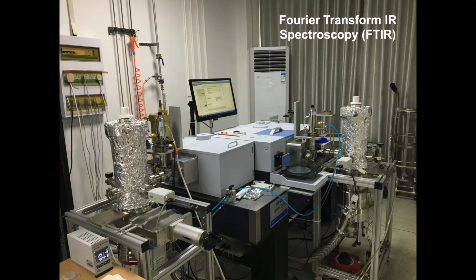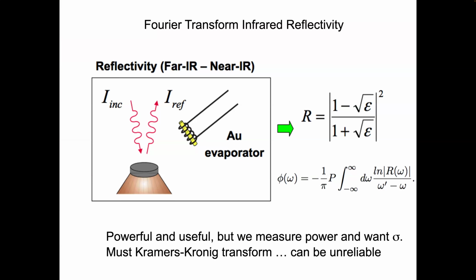And here's an example of an experiment that was done, not by me, but in Dirk van der Marel's group some years ago. The way these experiments are very often done is you measure the light which falls on a sample, and the light is reflected from the sample. And then you go in with a little bit of gold and you evaporate gold on top, and you do the experiment again, and you look at this ratio. That gives you the reflectivity as a function of frequency. But we want a complex quantity. We want a sigma 1 and sigma 2. We want to measure two things.